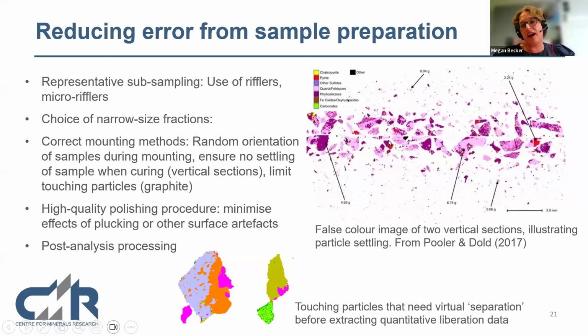If I were to analyze only that surface, I would get results that were very wrong and completely overestimate the abundance of the heavier material. If I analyze only here, I will completely underestimate the mineralogy. The point is to get this representative cross-section. So if I'm mapping this material and that material with my AutoSem EDS, I'm going to get a good representation.